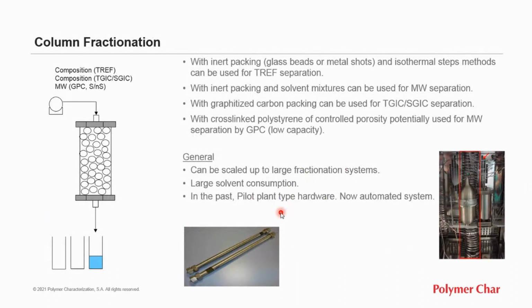For a larger scale fractionation, we developed a column fractionation apparatus, which also automates the fractionation process. And depending on the kind of column installed, it is used for TREF fractionation with inner packing, molar mass fractionation, even interaction chromatography modes for lower crystallinity polymers are possible. The solvent consumption is rather large, 5 to 10 liters per fractionation, and also the time for full fractionation could be 1 or 2 days. But it can handle up to 20 grams